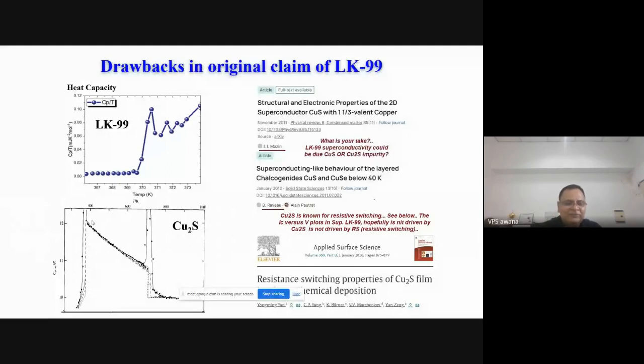And if you see even the heat capacity of copper sulfide, it matches very well with the LK-99. This was the structural phase transition of copper sulfide. The problem of LK was this: they could get the resistive transition at 100 degrees centigrade. They could get some anomaly in heat capacity at 100 degrees centigrade. And R equal to 0, they did not worry much.